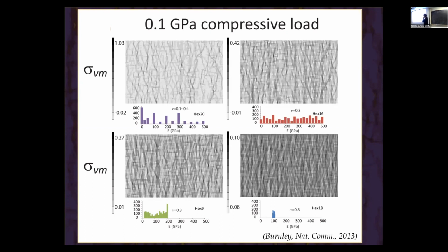But anyway, so you can see here we have a factor of 4 amplification. Here we have a factor of 3. And here we have very, very little stress amplification, right? So we see a modulation in the stress, but that modulation is quite small. And then over here, we have a very large modulation in the stress states within the material.